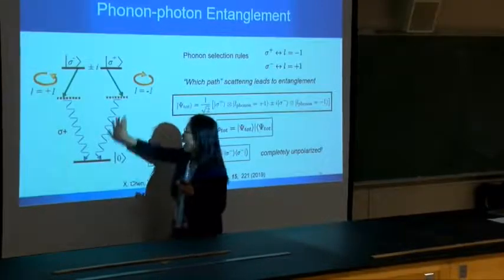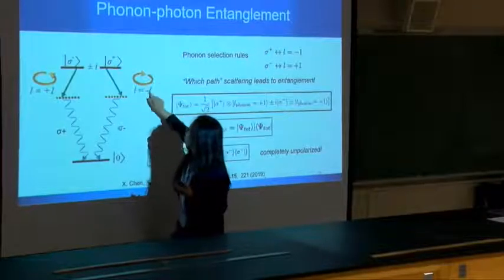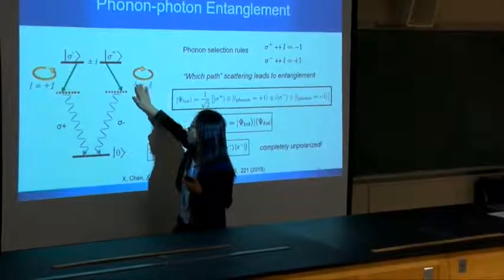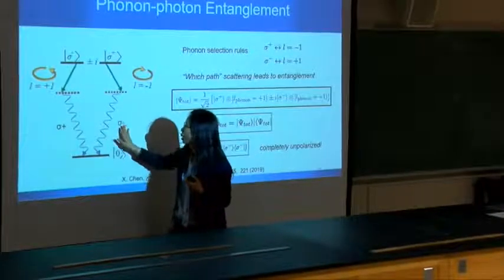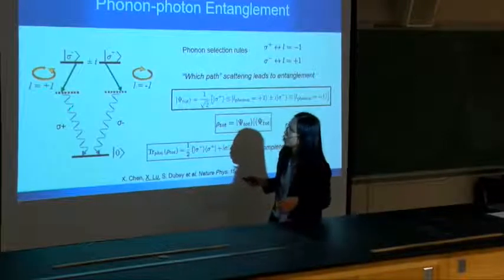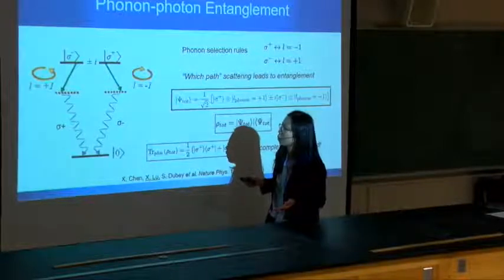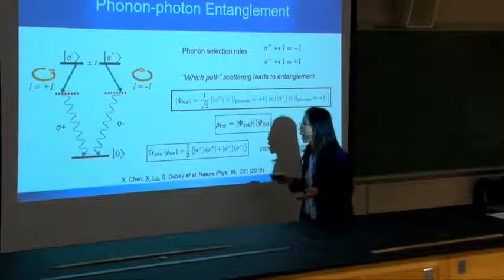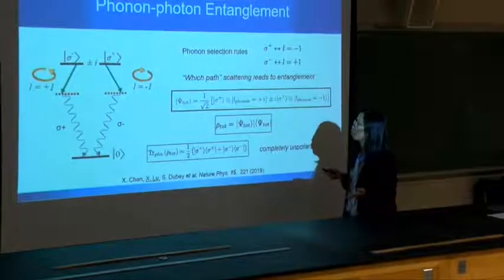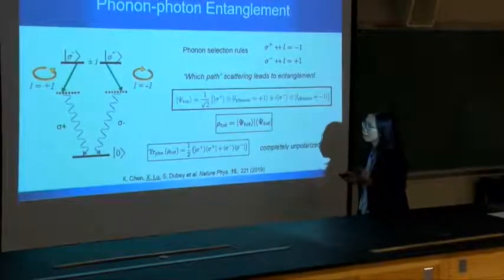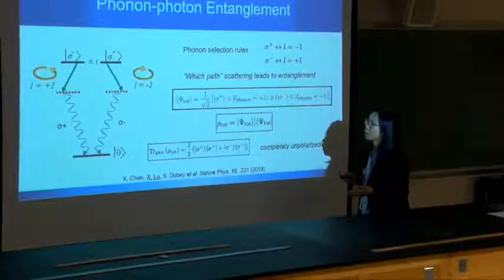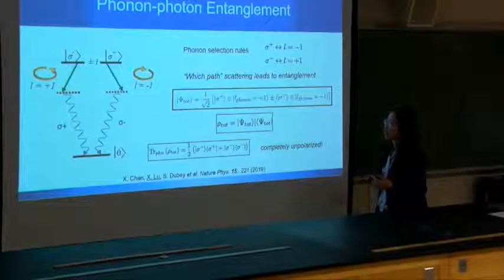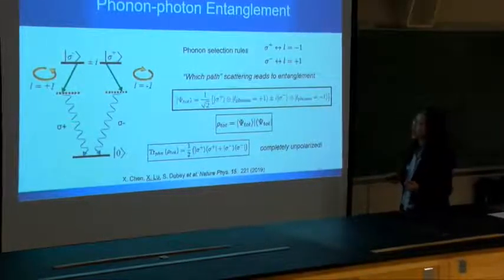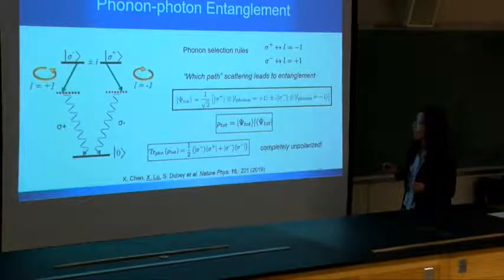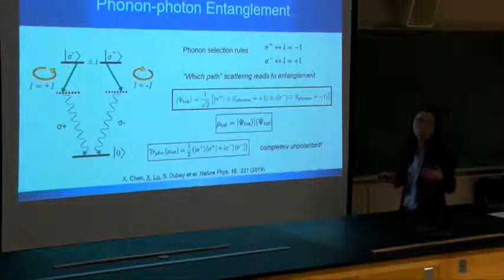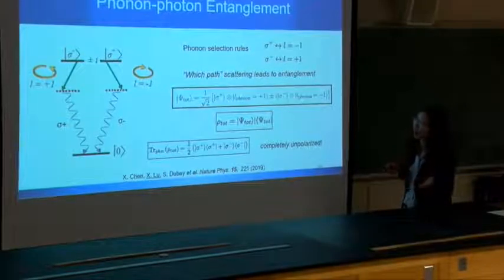So here, if we just look at the right branch, a sigma plus photon scatters or emits a phonon with minus one angular momentum, and it will become a scattered photon with sigma minus. And similarly, from the left branch, a sigma minus photon interacts with plus one phonon and scatters to a sigma plus photon. So these two paths at zero B field are indistinguishable. And as we don't have access to the phonon information, we need to trace out the phonon system, and what we actually get is, in fact, unpolarized emission. That's why we observed unpolarized emission earlier.